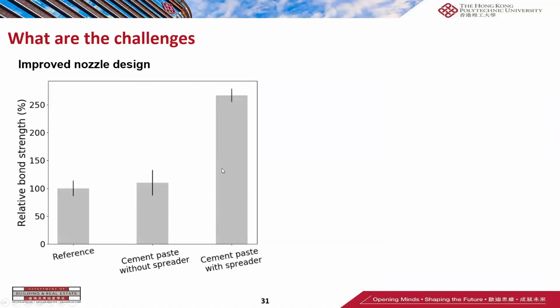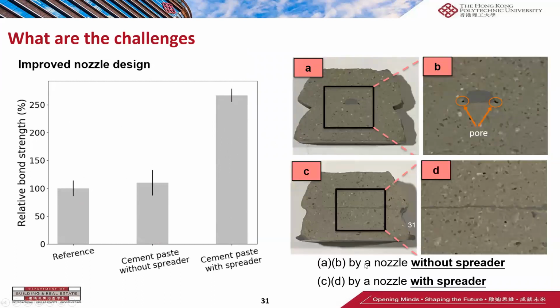You can find that with the adoption of the spreader in the nozzle system, the bond strength can be increased by as high as 250% compared with that of the reference group. This is mainly because when the spreader was adopted in the nozzle system, the cement paste can be evenly dispersed at the interface, and finally, the cement paste can act as an effective bonding agent between the interface to enhance the bond performance.